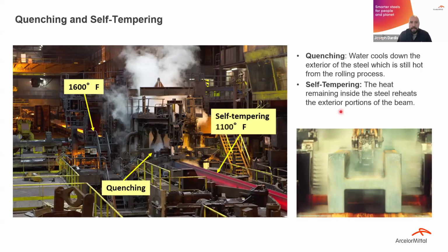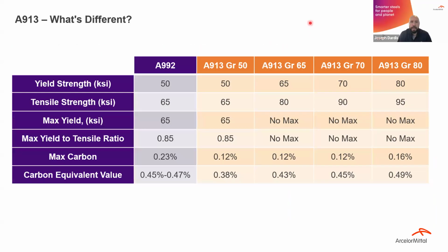We'll have to go to the next slide. Now, the other thing that's different is, because QST gives us all that additional strength, we actually don't need nearly as much carbon in A913 relative to A992 or our conventional A572 grades. So you'll see there down at the bottom, our max carbon percentage is significantly lower for all A913 grades. It's about half for grades 50 to 70, and then about 2/3 for grade 80. And ultimately, what that means is you're putting less carbon in the steel. It's not as hard.